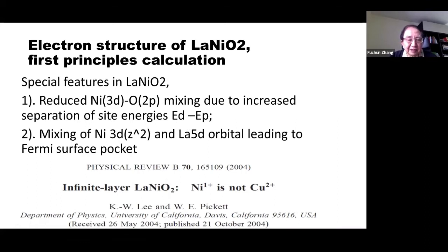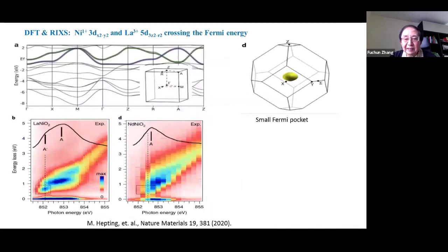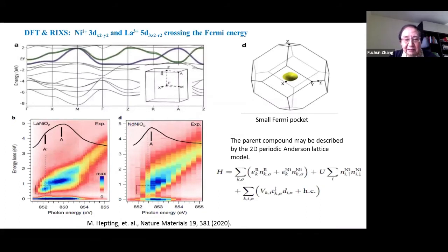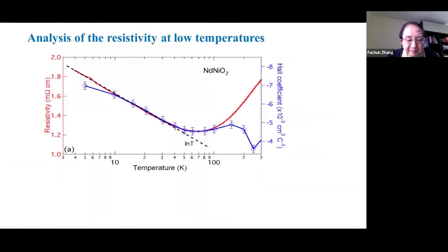The second, probably more important, is mixing of nickel 3d x2-y2 and lanthanum 5d orbital, which will lead to a Fermi surface pocket. That means the lanthanum 5d electron comes out. If I use neodymium, it's the same: a 5d electron will come out. So things are more complicated than cuprate. And the resonant inelastic X-ray experiment indeed found a small Fermi pocket. That was carried out by Hepting's group at Stanford. That explains the difference between the parent compound of nickelate superconductor and the cuprate.